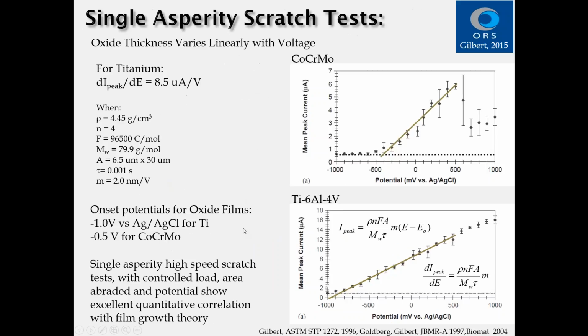And so this model is very helpful and in fact shows us the behavior of titanium and cobalt chromium as a function of voltage. And in fact, what we see is, as predicted, the currents are linear with voltage, as I showed you earlier from the high field growth model. And when you put in the known values for these parameters that you either measure or come from the literature, you get the line that overlays that data. And so that's not a curve fit, that's simply putting in the values of the density of the oxide and so on, and you get that curve.